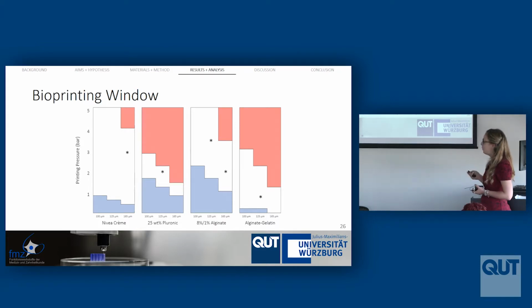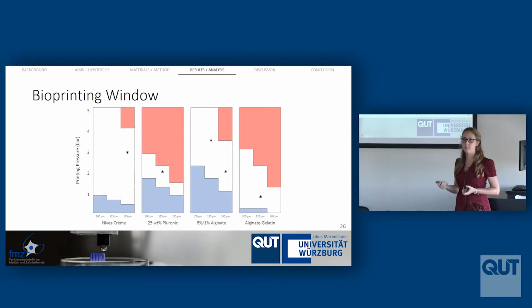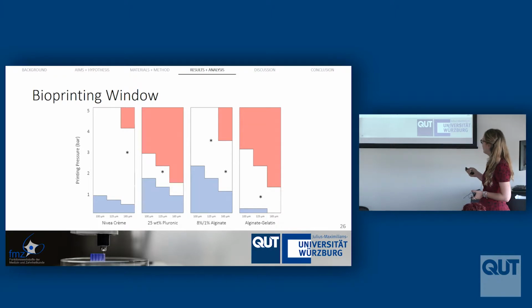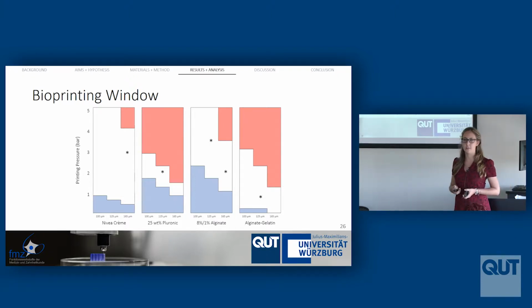And so I applied this to all of the different materials that I screened to check if it actually works. And sure enough, let's look at the Pluronic, for example. In all these cases, this isn't enough printing pressure to get it. There's a nice window here where it works. And then here, the printing pressure would be far too high and we can't print structures anymore. And so I showed you those nice pictures of the results that I got of those structures. And it turns out that every time they fell within the bioprinting window.